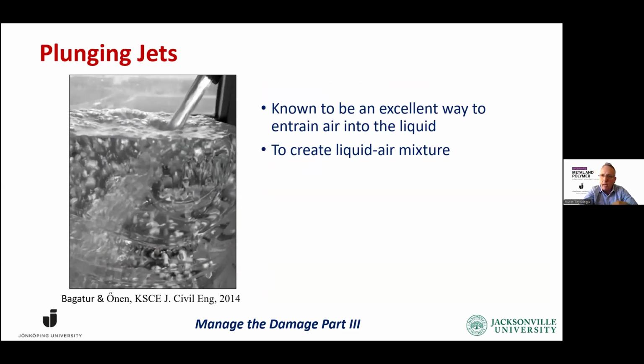We saw how this melt transfer, when it went in, there was a turbulent reaction in the ladle, in the crucible below in the holding furnace. And that's called a plunging jet. When you drop a jet from a height, it goes into another liquid. It's known as a plunging jet. It's a great way to entrain air into the liquid. It's well known as a fantastic technique to create a liquid and air mixture. Well, we don't want air in our aluminum castings and liquid aluminum, because that air is going to leave a trail, and in this case, it's going to be a bubble trail.